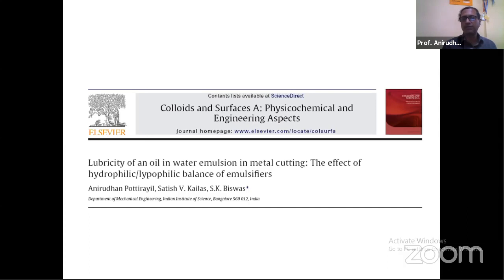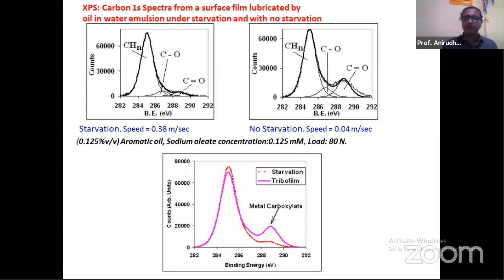We had done XPS to investigate the chemical formation which happens when we do tribological experiments using oil in water emulsions, the applications being in the area of metal cutting tribology. So on top, it shows the carbon 1s spectra corresponding to two different tribochemical films. The one on the left shows the carbon 1s part of the XPS data when there is starvation. And the one on the right shows the carbon 1s data when there is no starvation, meaning it is well lubricated.